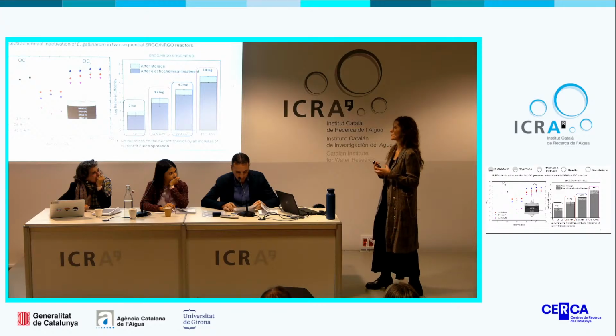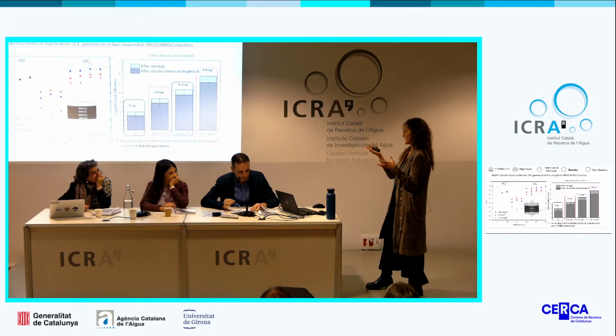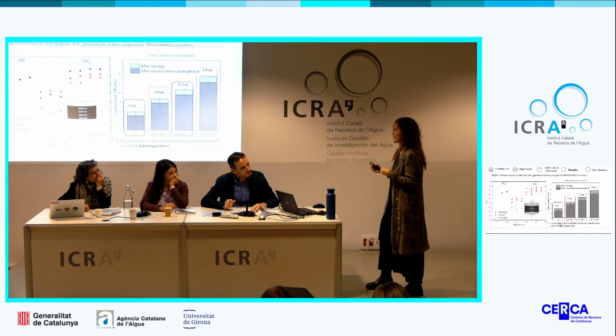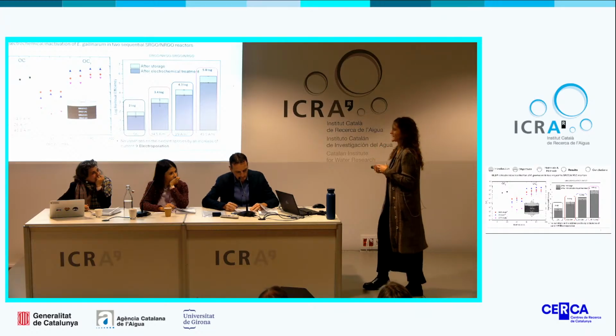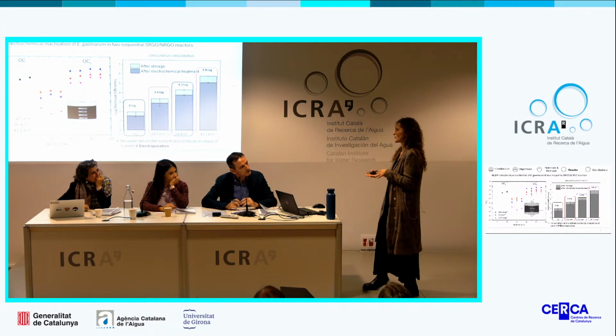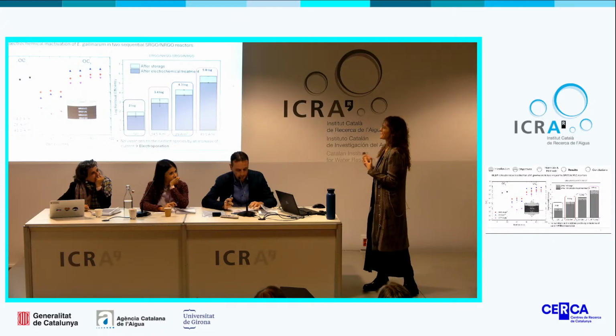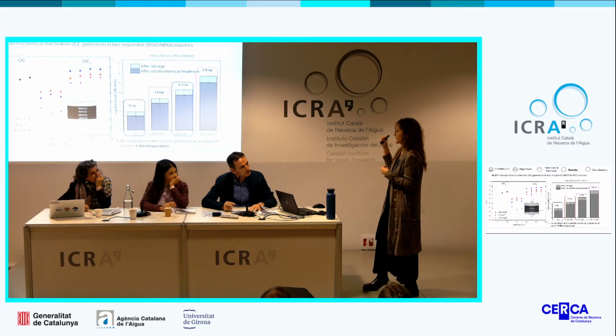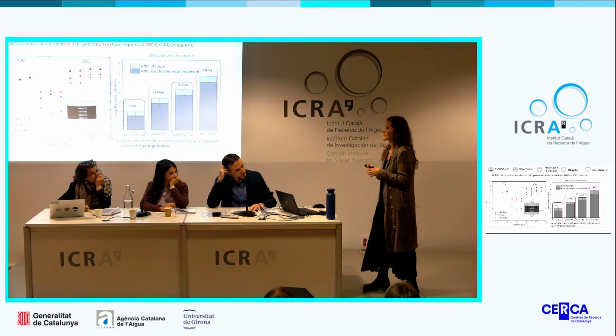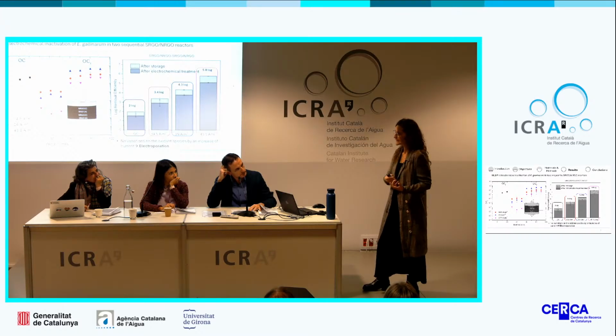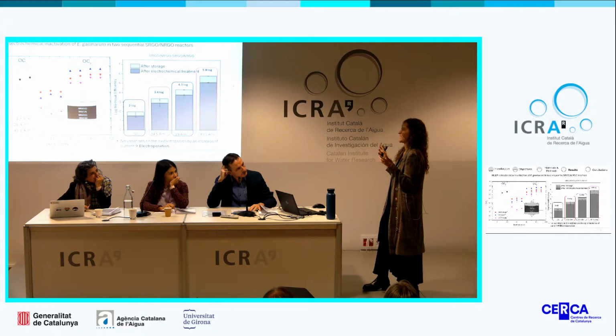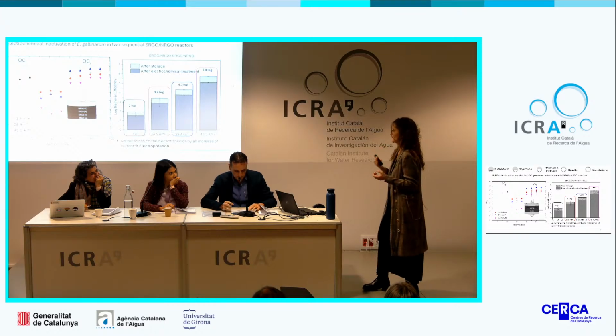In the case of N doping, according to the literature, and as shown in these schemes of the reactor, we are always using NRGO as a cathode. This is because, according to the literature, hydrogen peroxide as an oxidant species is favorably produced when we dope the reduced graphene oxide with nitrogen. So that's why we decided to synthesize this as a cathode. In the case of boron, it was previously investigated to be effective for some pharmaceuticals.